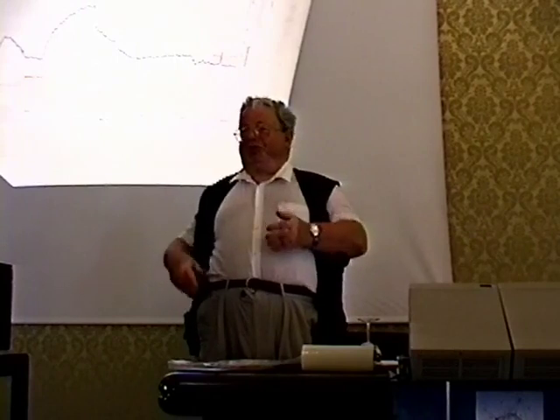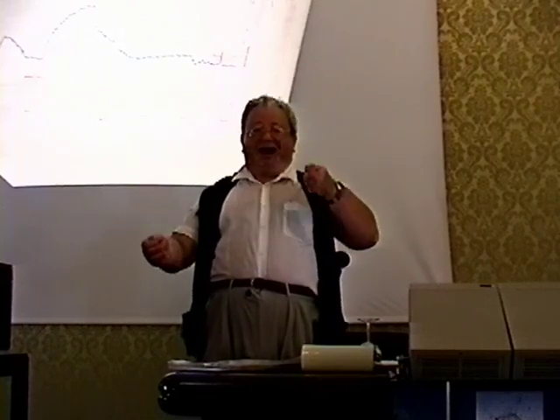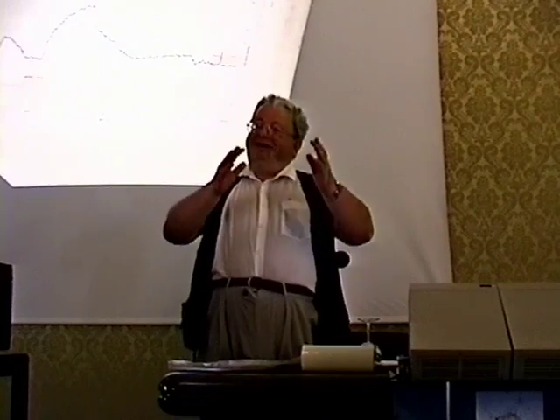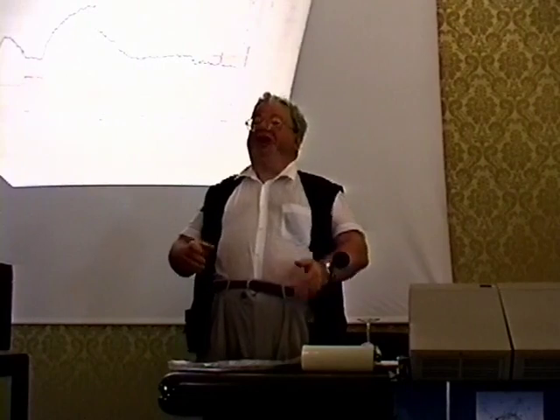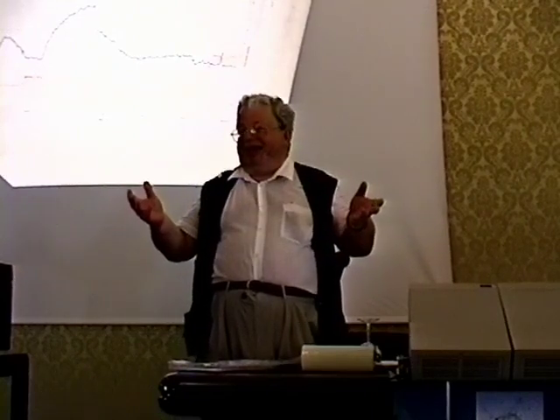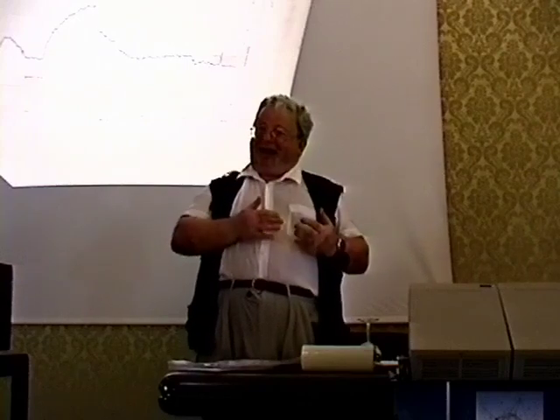A more refined version, which I anticipated in discussing the depression of the peak, is that hydrogen is both in a coherent and in a non-coherent situation, because since the temperature is not absolute zero, of course the thermal fluctuations extract particles from the coherent picture. So as in water in the old-fashioned Röntgen model, there is a coherent part which is described by this function, and a non-coherent part which behaves in a sense as the alpha phase, which is a gas, a non-coherent fraction. By increasing temperature, the non-coherent part acquires importance at the expense of the coherent part. So there is a maximum temperature where coherence disappears altogether, and this explains the critical factor.